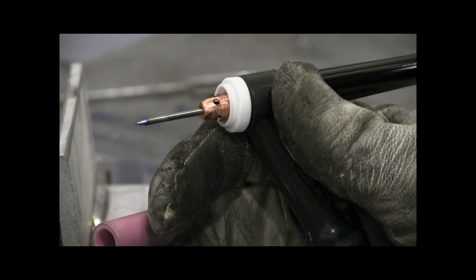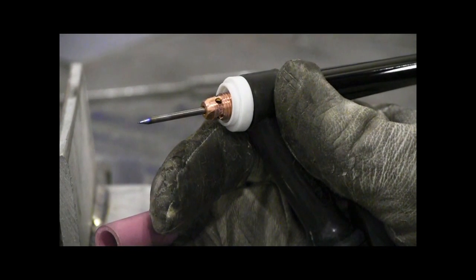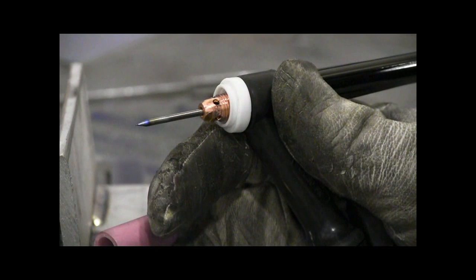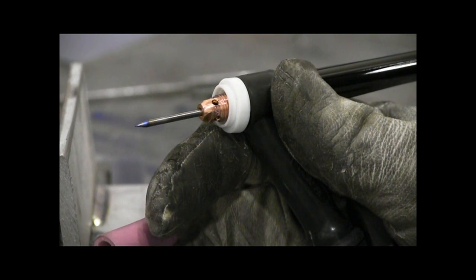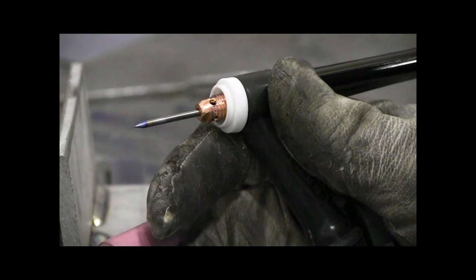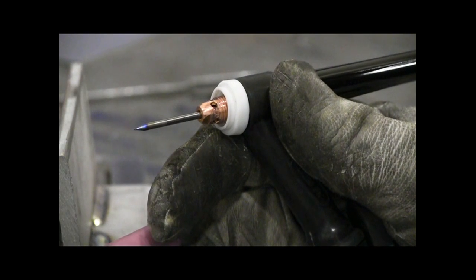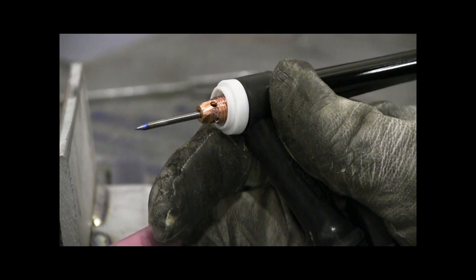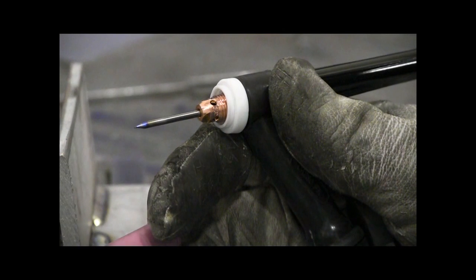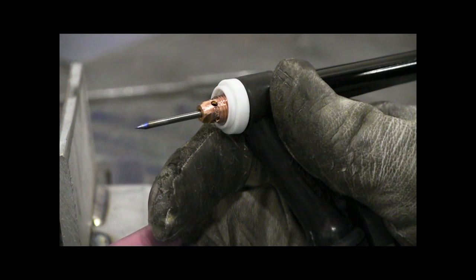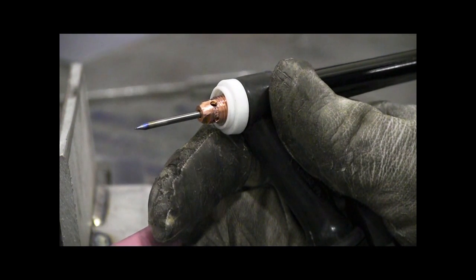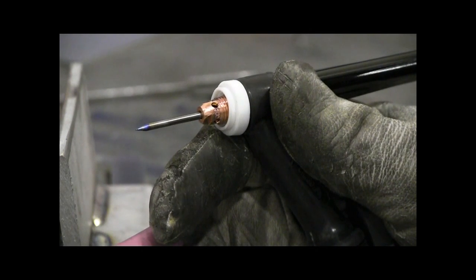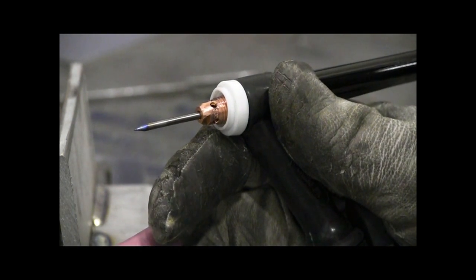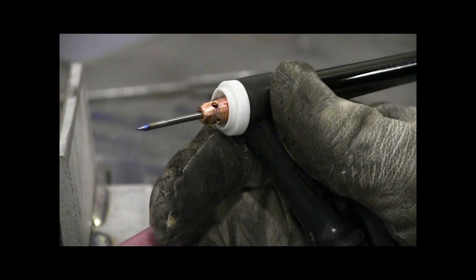And so now we can see, just after a few seconds less of post flow, we've got a tungsten where the tip has turned blue and deep purple, and that's evidence of oxidation and not enough post flow. So at the end of the day, no matter where you set it, if when you get done welding your tungsten is blue or purple, that's an indication that there could be inadequate post flow. So then just adjust the post flow settings accordingly.